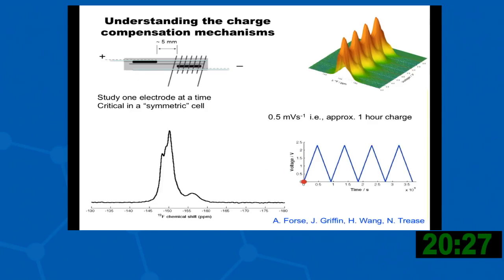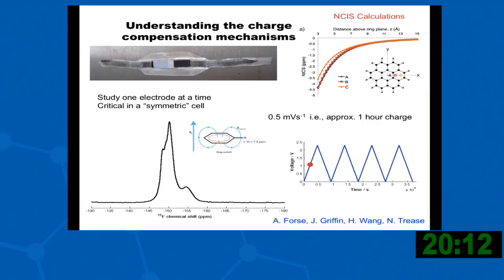We can now look at this inside our material. So now what we're doing is we're making a supercap, and we're putting the supercap now inside the NMR spectrometer, and we're going to charge the supercapacitor positively. And so what you're seeing now is the positive electrode and the change in the fluorine signal of the BF4- as you go from 0 volts up to positive volts. And so the most apparent thing that you see is a shift of the peak that I told you was inside the pores. And what you're watching is, interestingly enough, the change in the local environment of this signature.